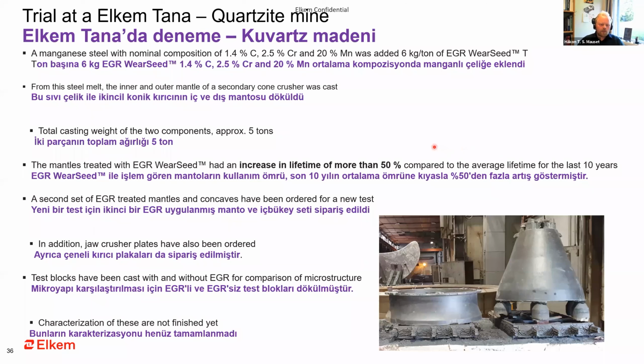And so the mine decided to order a second set of these EGR treated mantles, and they will be put into operation quite soon. And we hope, of course, that we get similar numbers or even better. And hopefully we will do several trials up there to see that we get the same effect. And in addition, they have also ordered plates for their jaw crusher. And these are quite big plates. They're around 2 to 3 tons per plate. And they will be put into operation quite soon as well.